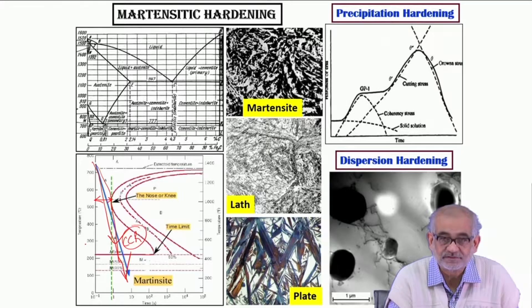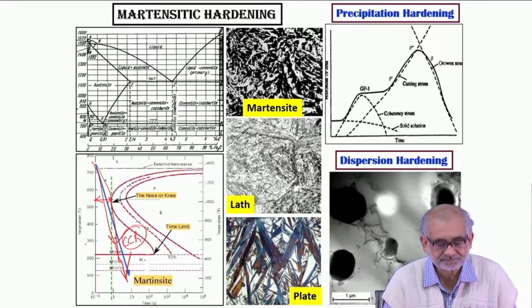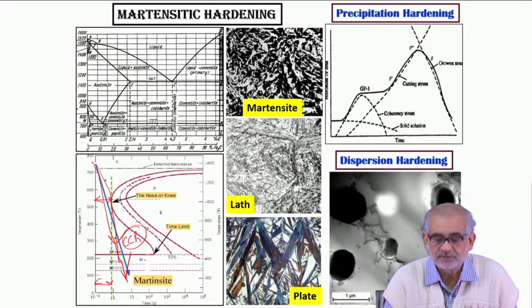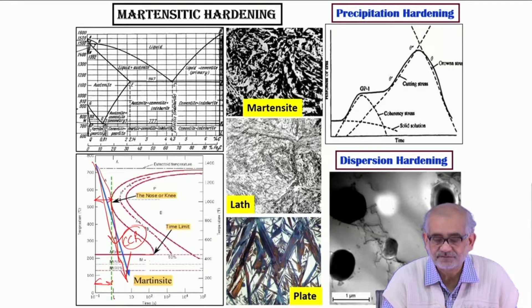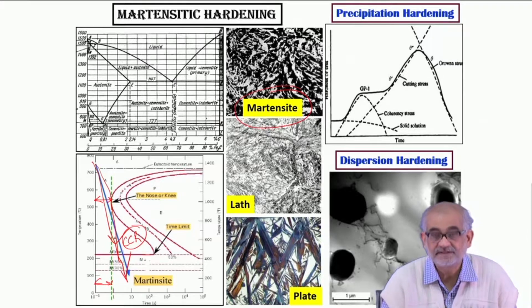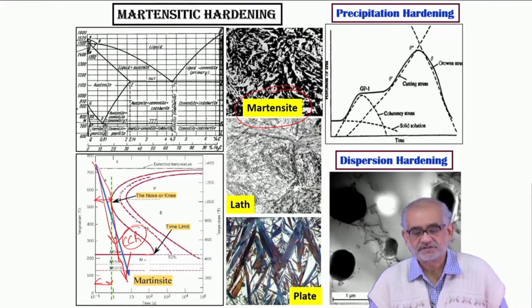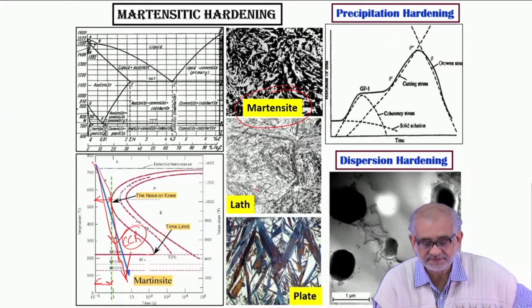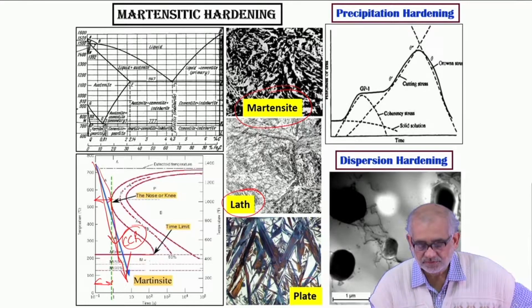So in other words we have to adopt some drastic quenching because this time period is very very small. When we quench then we convert the surface into martensite - that is our desired microstructural product. And martensite can appear either in lath morphology or in acicular or plate morphology.